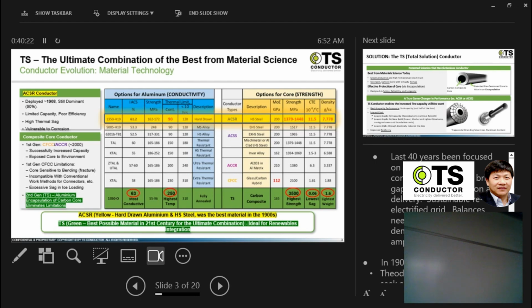The other challenges are these type of composite core with the carbon fiber and the glass fiber being parallel to the axial direction, which is normally called unidirectional composite, they're exceptional in the fiber dominated property like strengths. But when you compress on them from the ends, or when you bend it, the compressive strength is actually lousy because compressive strength is dominated by the matrix, organic matrix material. It's only about 60 to 70% of the tensile property. So what it means is you will always prematurely fail on the compression side when you bend it. So you have a compromise situation where if you don't manage the bending angles or the bending radius properly, if you have a sharp edge situation like the table edge here, you bend it, it's going to snap. That has been one of the Achilles heel in that type of product.